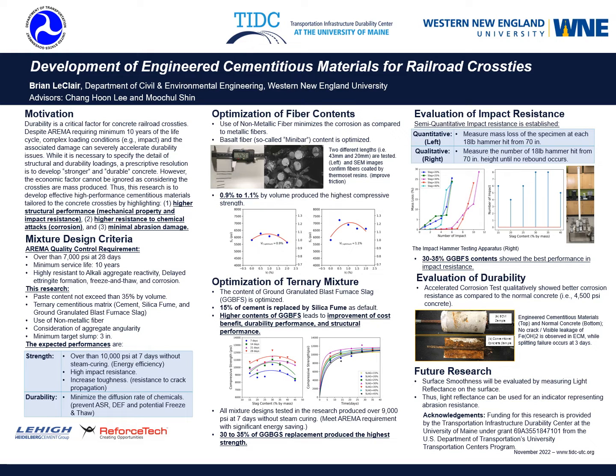Lastly, we wanted to test the durability of the concrete to corrosion. As you can see, the engineered cementitious materials at the top performed much better than the basic concrete mix at the bottom. These pictures were both taken only 3 days in the accelerated corrosion chamber. For future research, the smoothness of concrete samples will be evaluated. This will be done with a light reflection sensor, with the goal of smoothing out the concrete mixes and minimizing abrasion damage of the railroad crossties.